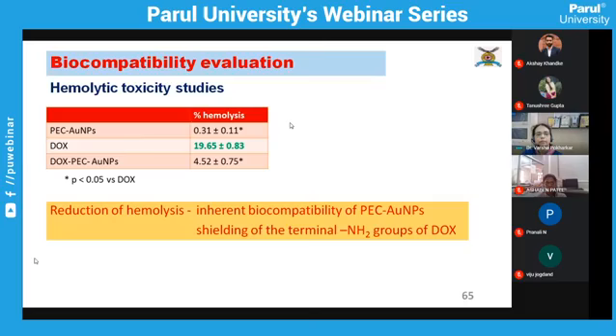The biocompatibility we have done by simple hemolytic studies, and here we have seen that whereas doxorubicin is quite toxic, the percent hemolysis is around 19%. The pectin reduced gold nanoparticles have almost negligible hemolysis, whereas the doxorubicin when loaded onto the pectin reduced nanoparticles has considerably reduced hemolysis. This reduction in hemolysis is because of the inherent biocompatibility of the pectin reduced gold nanoparticles, which leads to the shielding of the terminal amino groups of the doxorubicin, which are responsible for the toxicity.